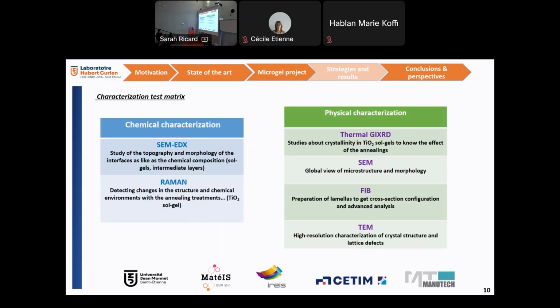So to be able to follow all of these results that we are obtaining in this project, we present a characterization test matrix. We are doing chemical characterization, for example, scanning electron microscopy to follow the global view about the morphology, the texturization of the samples. We are using EDX to identify the chemical elements that we have on the top and in the interface layer. We are using Raman spectroscopy because we are working with TiO2, so we should know the crystallinity of our sol-gel coating related with the hardness.